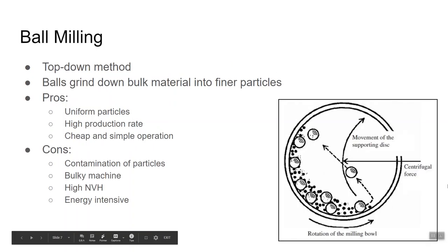Ball milling. Ball milling is a top-down method, and this means that bulk material is reduced into smaller particles. A ball milling machine consists of a horizontal rotating cylinder into which the bulk material and small balls are placed. The cylinder rotates and the ball motion due to gravity grinds the bulk material down into nanoparticles. The balls can be made of ceramic or stainless steel.